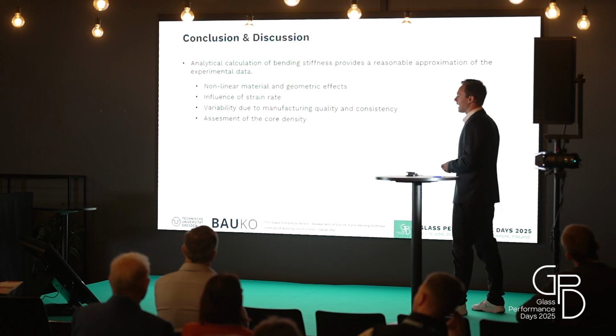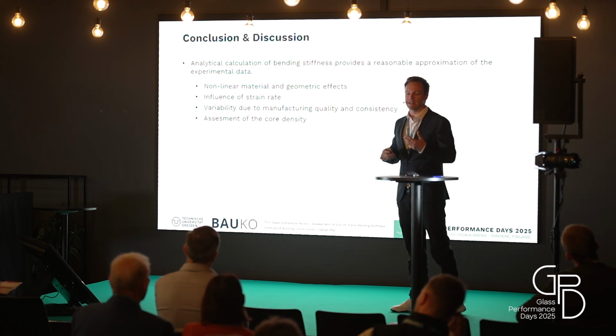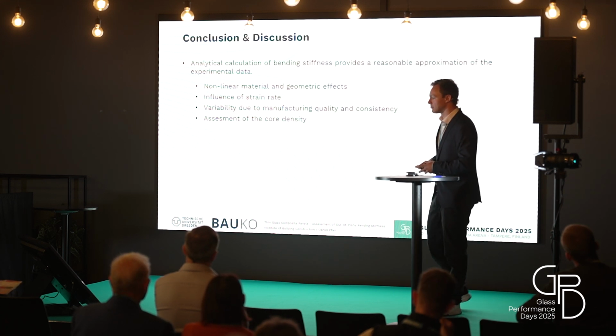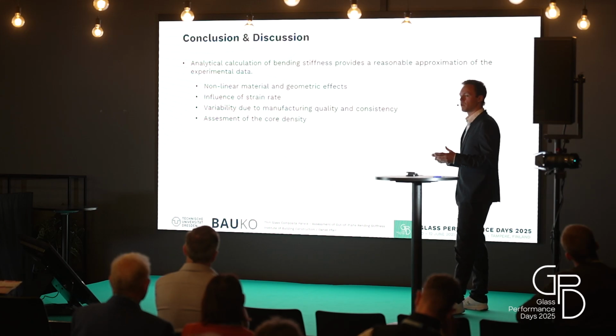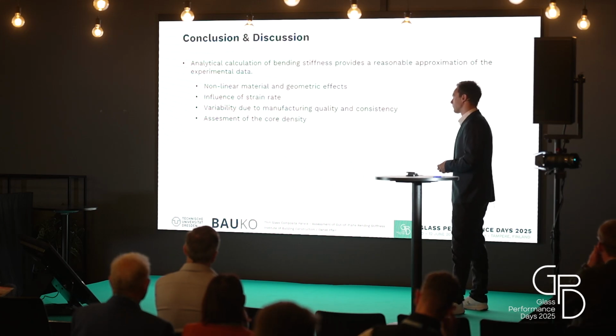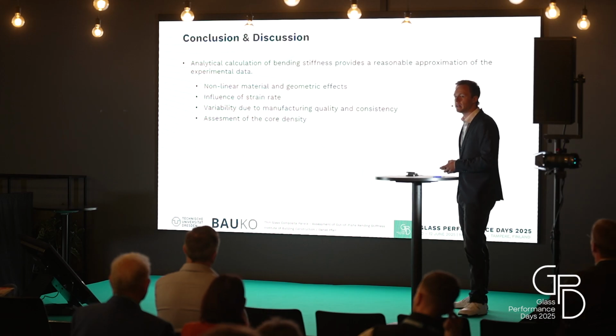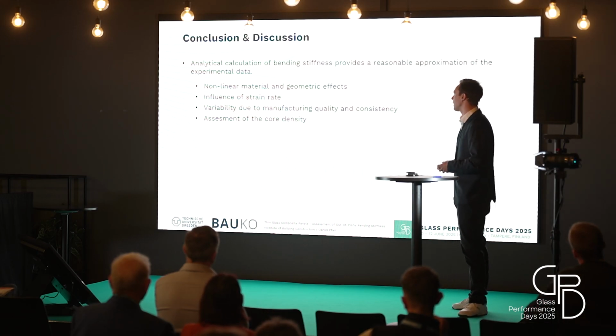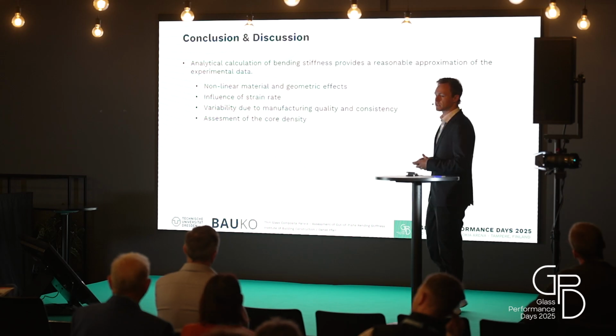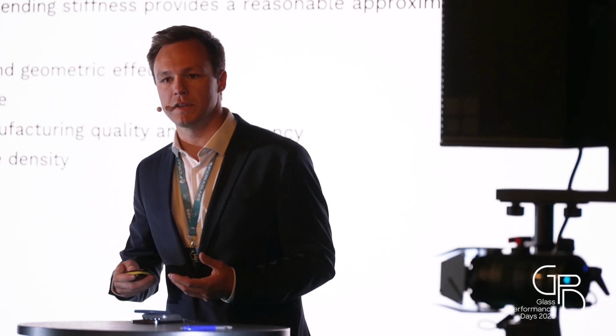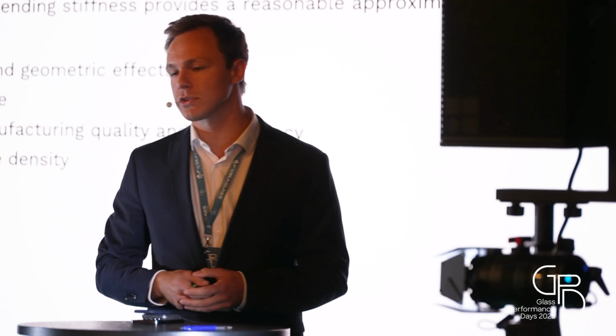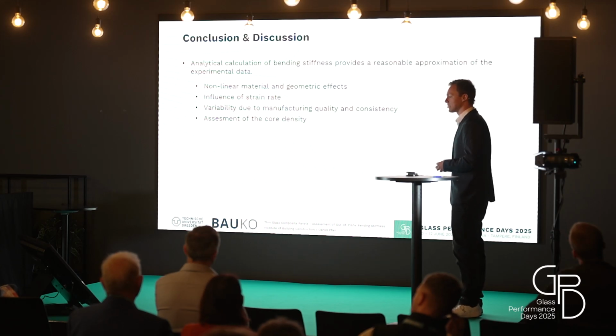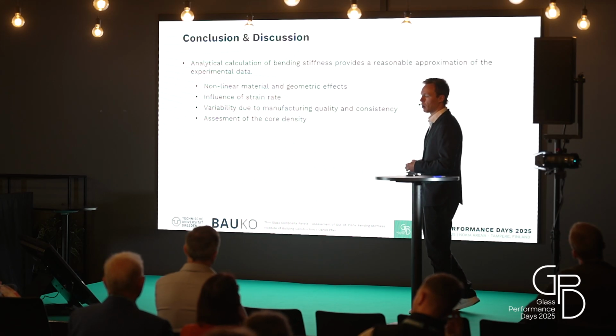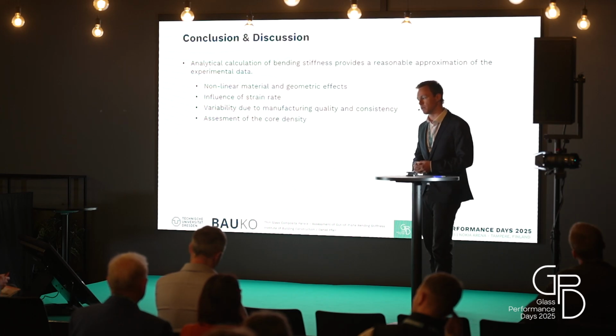I think we can say that the analytical calculation of the bending stiffness already provides a reasonable approximation of the experimental data. But of course, there is some room for improvement. For example, the nonlinear material or some geometrical effects, which we have not covered in the calculation. The influence of strain rate could be a very important one. The variability due to manufacturing quality, because of the 3D print or the application of the adhesive, could play a role here, and the assessment of the core density, which can be quite complex if we are changing it from a honeycomb to a different one.